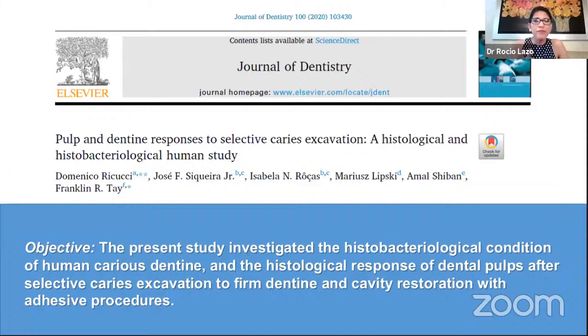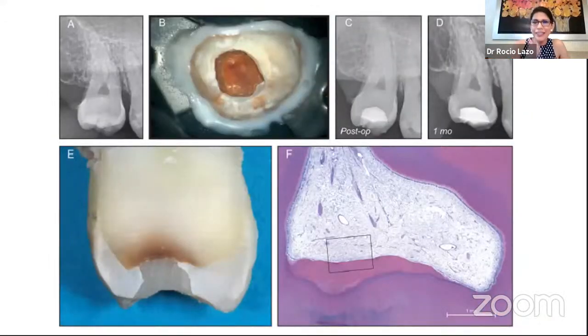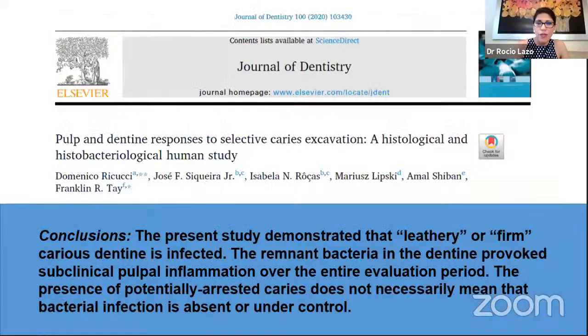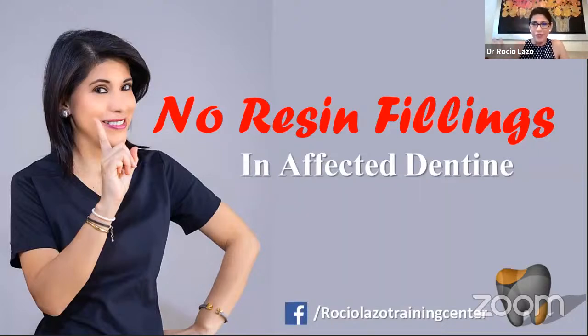So why did Dr. Ricucci say that? Because in his research, he applied resin in affected dentin. And look here, what happened in the case that I showed you is the same that happened in Ricucci's cases: metalloproteinases wake up, degradation of the adhesion, and of course secondary caries. Conclusion: no resin fillings in affected dentin, because this is what happens. So I presented both cases: classic glass ionomers in affected dentin don't work well, and resin fillings don't work well in affected dentin.